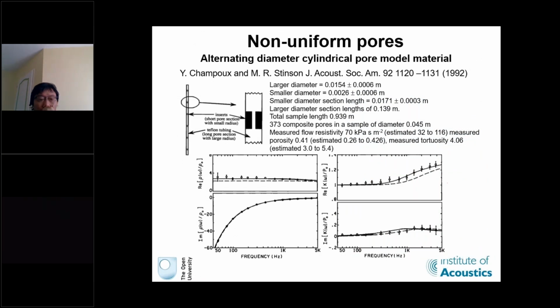So again, we go back in time to Champoux and Stinson, who went to the trouble of actually creating a material with non-uniform pores. I've forgotten now what materials they were using, but maybe latex, rubber tubing, and some other way of getting increased... I think they cut grooves in Perspex. Oh, Perspex, right, okay. And essentially they found that even when you had pores normal to the surface, this increases the tortuosity inside the material, and therefore you change the acoustical properties. And because they knew precisely what material they created and the characteristic dimensions inside it, they were able to predict what it should do in terms of the real and imaginary parts of impedance and the real and imaginary parts of propagation constant, and that fitted pretty well with the measurements they got. So if you deliberately create non-uniform pores, you can change the acoustical properties of a thin layer.